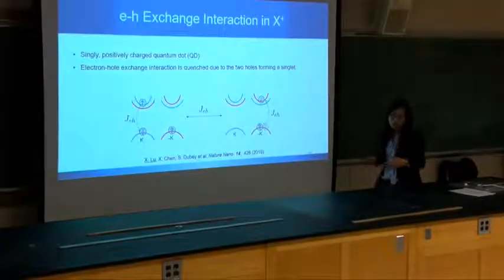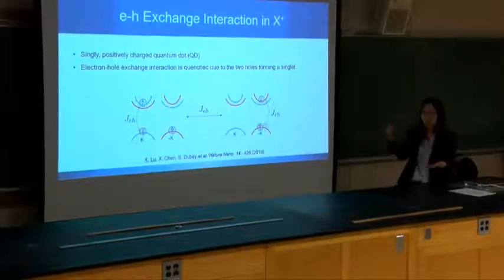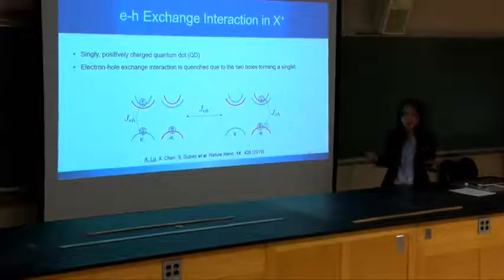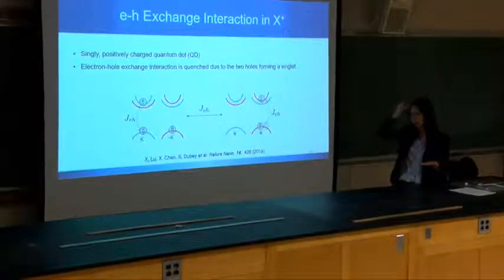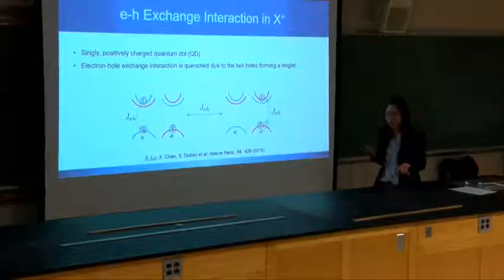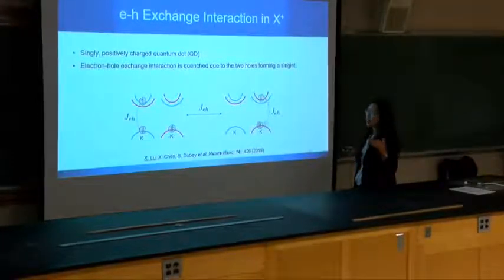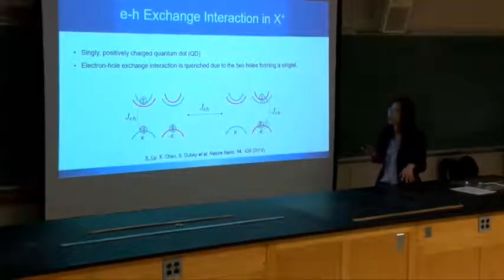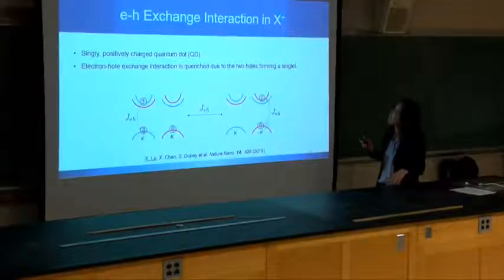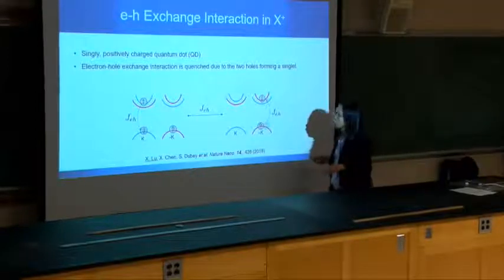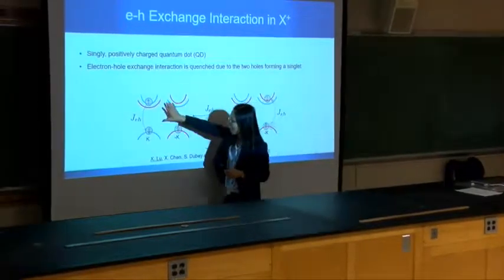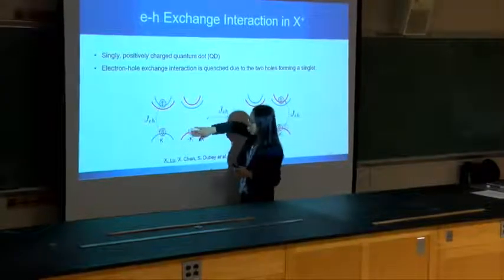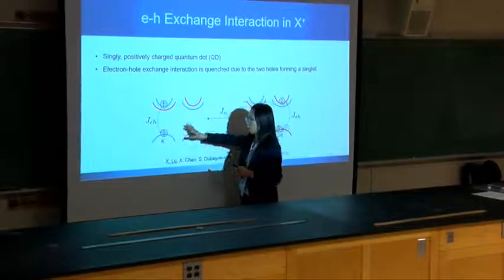Okay, so you may ask: it looks like the exchange is everywhere, and it looks like we can't initialize it in this layered material platform. But that's not actually true, because it is there for the neutral exciton, but we can actually create a singlet positively charged exciton to avoid this problem. For the exchange I introduced earlier, without this extra hole, which is a positive charge, of course it will have exchange and flip to another valley.